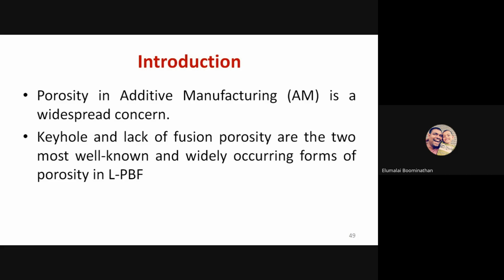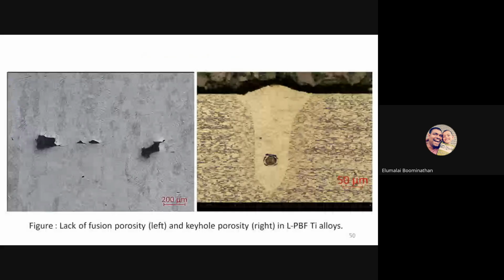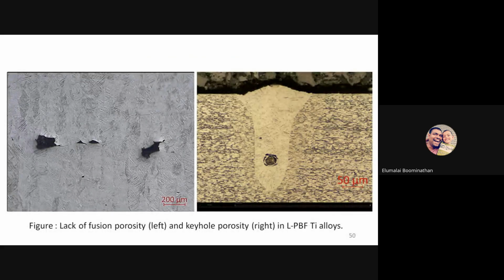There are basically two different types of porosities. One is lack of fusion porosity, where you use less power, and the opposite is keyhole porosity, where you use a high amount of power. The figure displays these two types. The figure on my left side is lack of fusion, and the right side is keyhole porosity. The lack of fusion porosity is due to the small amount of power used, whereas keyhole porosity is because of the high amount of energy used.